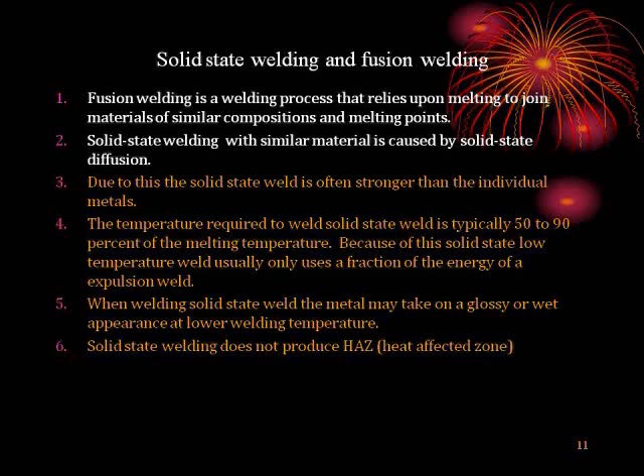The temperature required for a solid state weld is typically 50 to 90% of the melting temperature. Because of this, solid state low temperature welds usually only use a fraction of the energy of an expulsion weld. When welding a solid state weld, the metal may take on a glossy or wet appearance at lower temperature. Solid state welds do not produce HAZ, or heat affected zone.